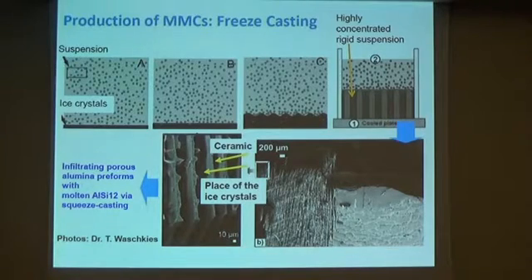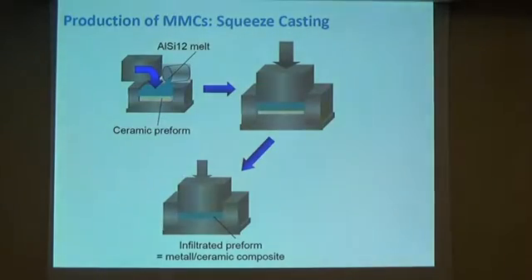And after freeze-drying, this open porous preform can be infiltrated with molten metal or polymer. In our case, it was aluminium alloy. So it is infiltrated with the molten aluminium alloy using a squeeze casting technique, and a composite is produced in which metal has replaced frozen water. So this method produces composites with high ceramic content, and the method is very cost effective, so such composites might be of interest to automotive and biomedical applications.